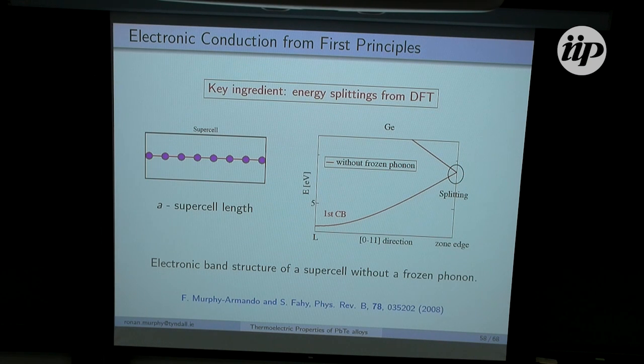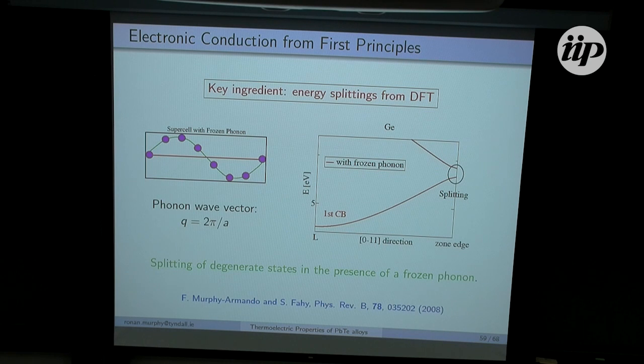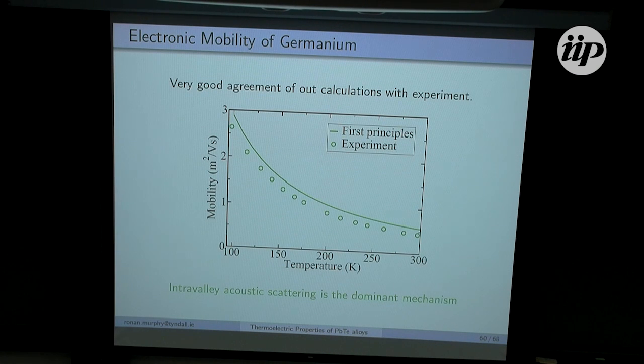Now, what we do is we then freeze in a phonon. You can imagine taking your atoms and displacing them according to the amplitude of this phonon. Then you recalculate the electronic band structure, and at the zone edge of the supercell, you get the splitting in the electronic states. You take this splitting and plug it back into some formulas which I won't dwell too much on, and you can calculate your scattering rates due to intravalley acoustic scattering. In the case of germanium, just to show you what that looks like, I have a calculated curve in green here, and some experimental data points in green, and for germanium we do get very good agreement. As it turns out, the dominant mechanism here is this intravalley acoustic scattering.